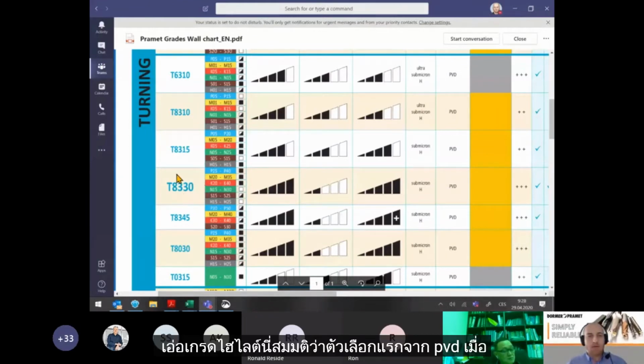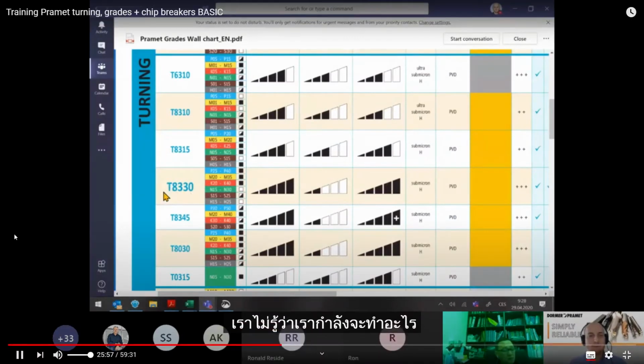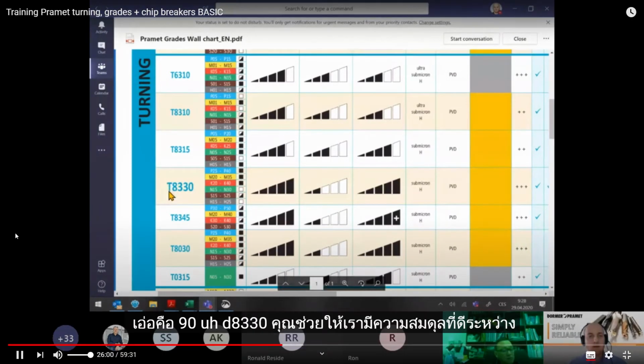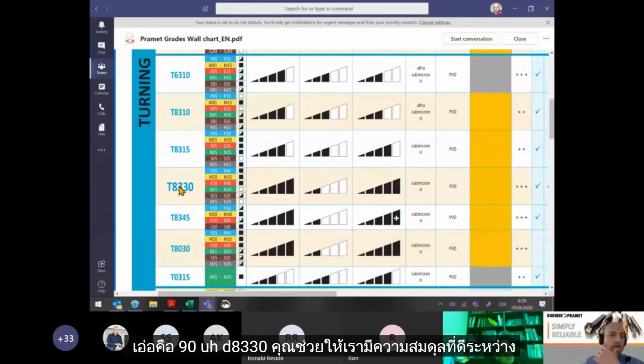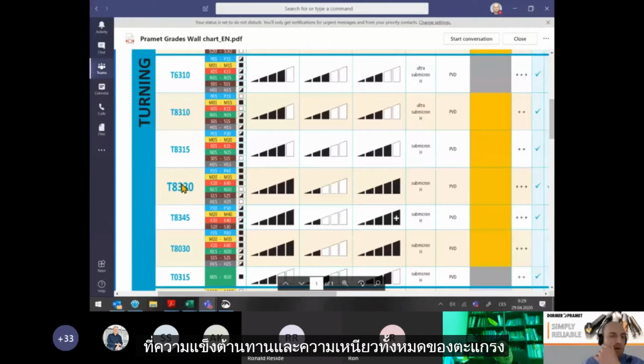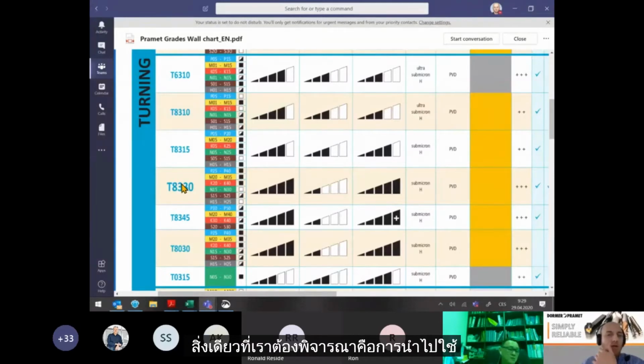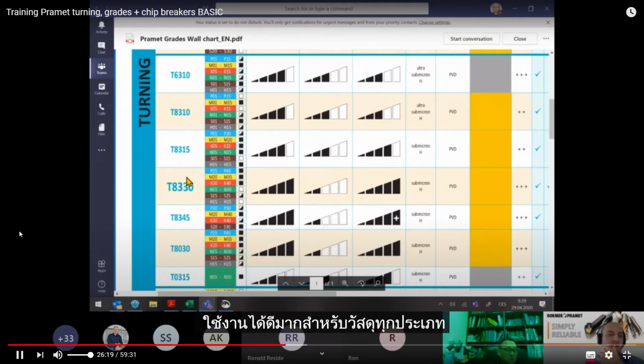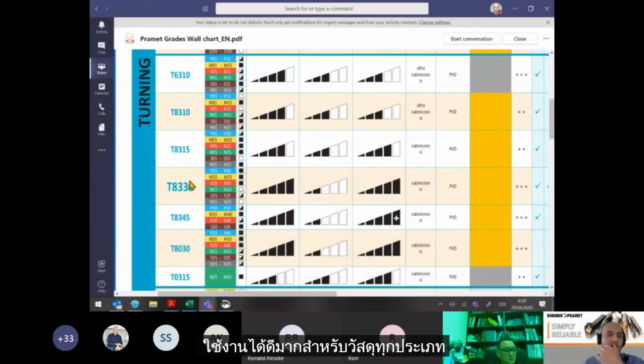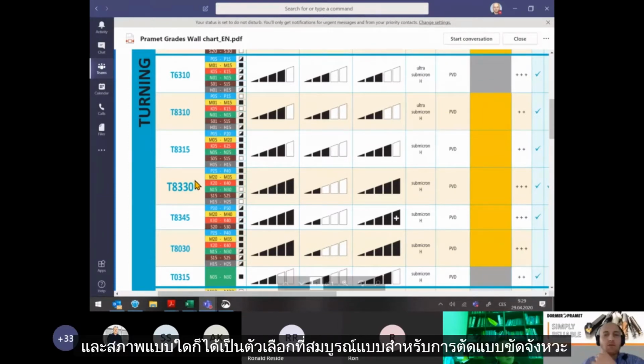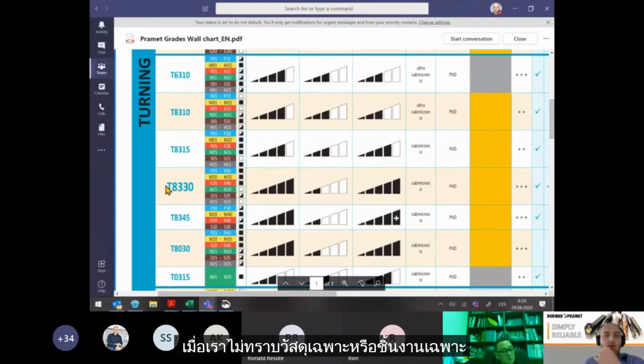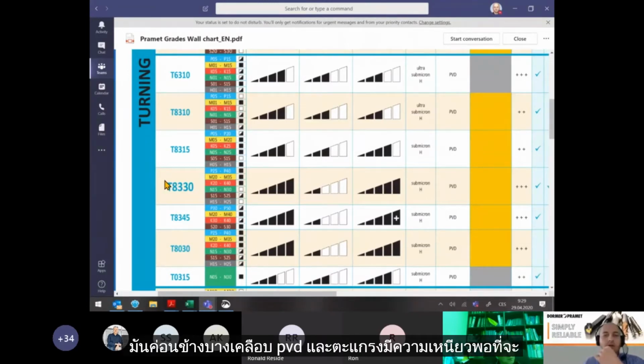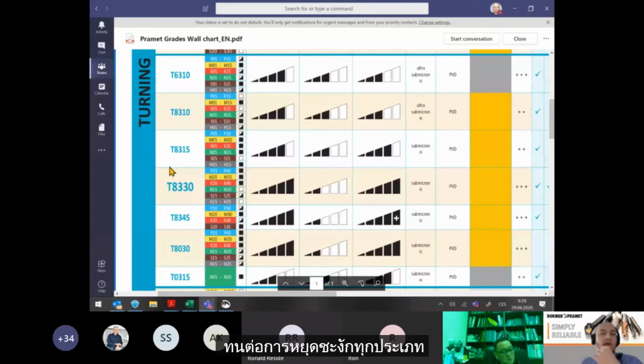Then the highlighted grade here, let's say the first choice from PVD when we don't know what we're going to do, is T8330, which gives us a nice balance between wear resistance, hardness, and also toughness of the grade. The only thing we need to consider is to apply, let's say, low cutting speed, and then this grade works very nicely for any kind of material and any kind of condition. It's a perfect choice for interrupted cut when we don't know the specific material or specific workpiece. It is a quite thin PVD coating, and the grade is tough enough to withstand any kind of interruption.